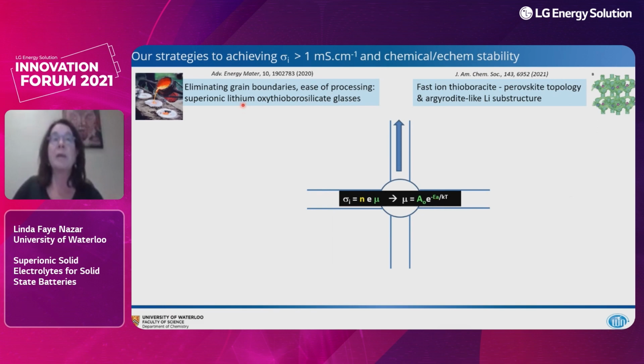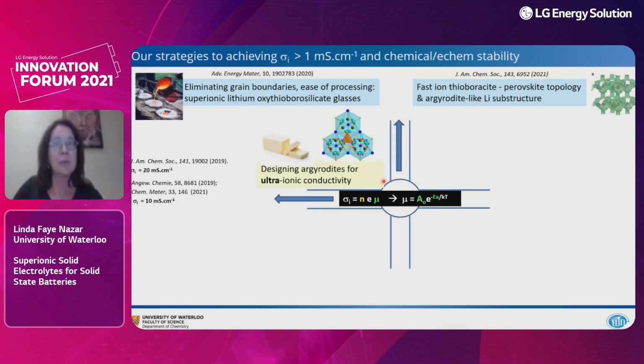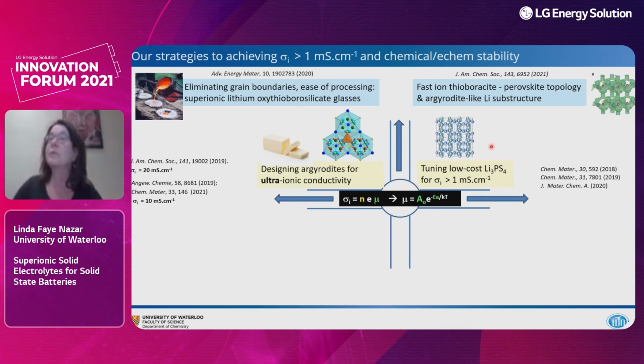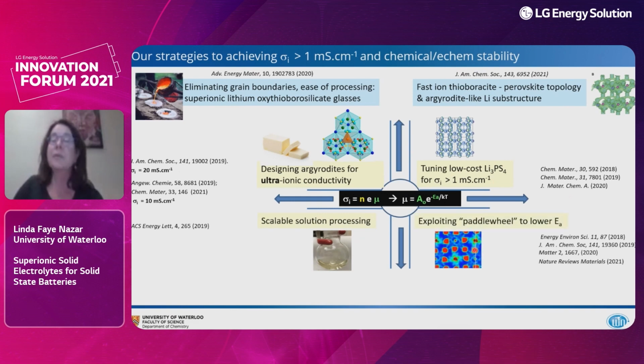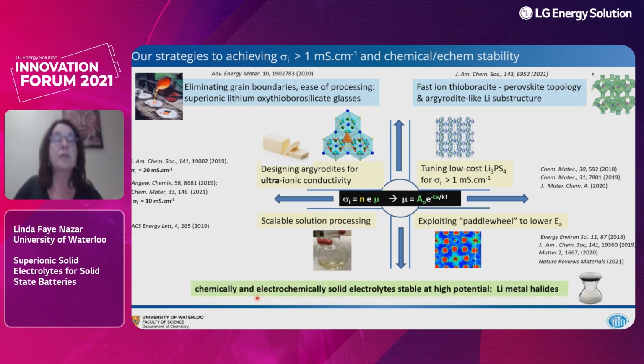So we've looked at eliminating grain boundaries by exploring superionic lithium oxythioborosilicate glasses. We've also developed some pretty unusual new materials, including this thioboracite, which has a perovskite topology, but an argyrodite-like lithium substructure. And we've explored a lot on argyrodites. I'll be talking about these in the next couple of slides. And basically achieved superionic conductivity upwards of 10 and even 20 millisiemens per centimeter. We've also been exploring the tuning of low-cost Li3PS4 to increase the conductivity. We've explored scalable solution processing. We've discovered some really interesting effects with what we call the paddle wheel rotation of anions to lower the activation energy. And then finally, as I said, trying to develop electrochemically stable lithium metal halides as electrolytes.